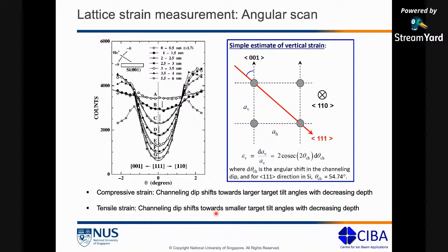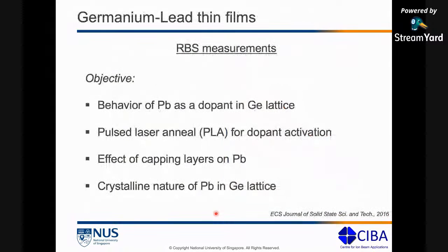And if it shifts towards smaller tilt angles with decreasing depth, that gives us a tensile strain. So by looking at which direction the dip shifts, that tells us whether it's compressive or tensile. Right. So this is one of the quite unique features of RBS and ion channeling, in that it gives us the ability to not only quantify, but also tell us whether it's compressive or tensile, the kind of strain that we have in the single crystal lattice, right? So that was the strain part of RBS and ion channeling.